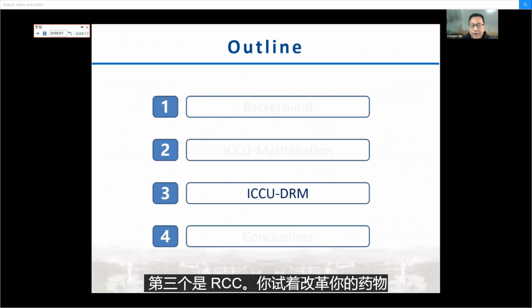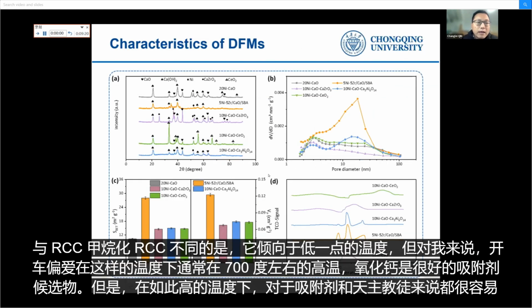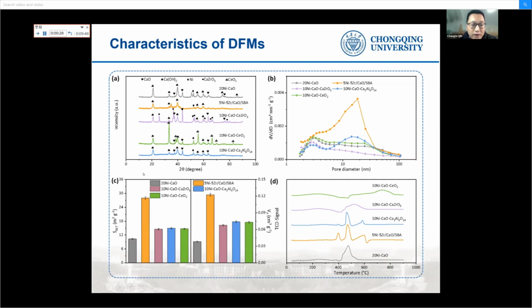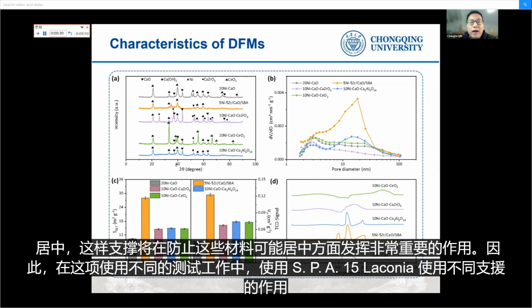The third one is ICCU dry reforming of methane. Different from ICCU methanation, which favors a lower temperature, dry reforming favors high temperature, usually around 700 degrees. At such a temperature, calcium oxide is a good sorbent candidate. However, at such a high temperature, it's very easy for the sorbent and the catalyst to be sintered. So the support plays a very important role in preventing potential sintering of these materials.